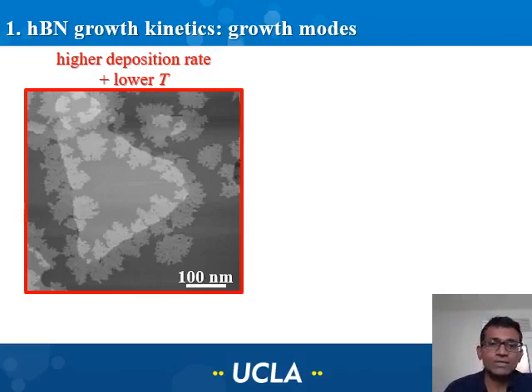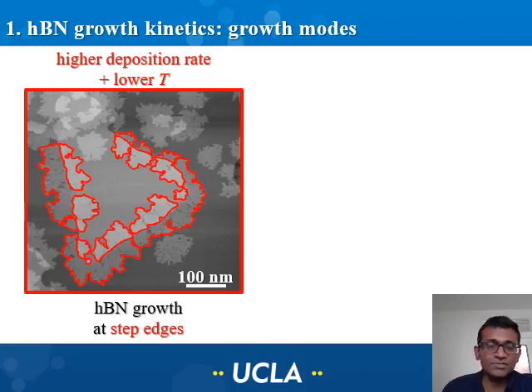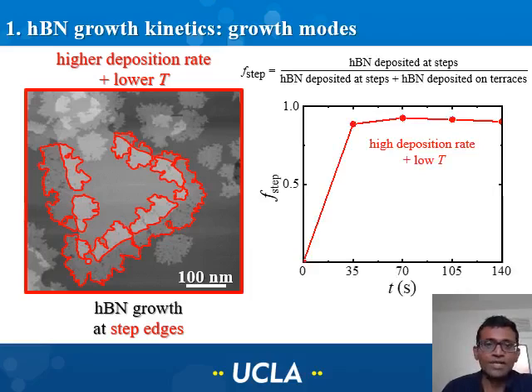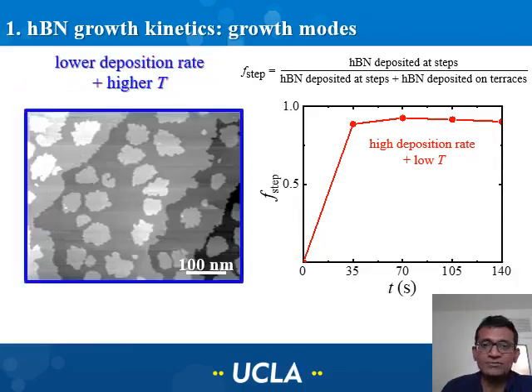And let's consider this one case where the deposition occurs preferentially at the step edges. I've highlighted here the deposition that occurred at the step edges. And now I'm going to plot the coverage along the steps as a function of time. Here, a coverage at step edges of 0 implies deposition occurred only on terraces. And if the step coverage is 1, that implies the deposition of hexagonal boron nitride occurred primarily at the step edges. And what we notice here is that in the time-dependent coverage, initially the step coverage